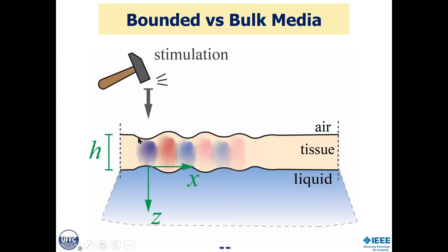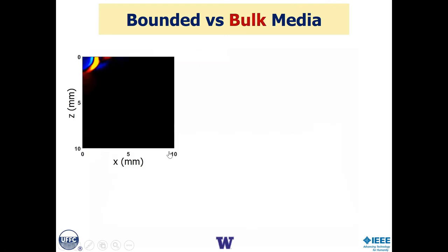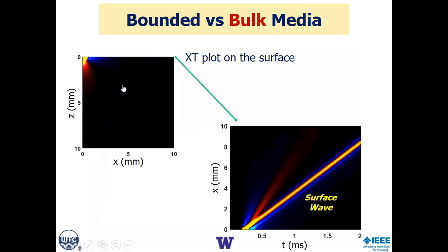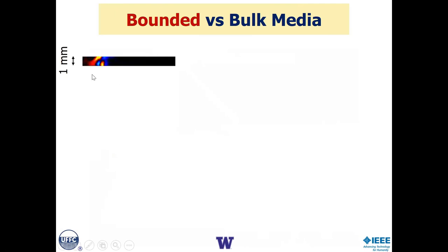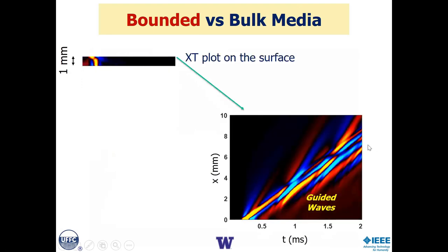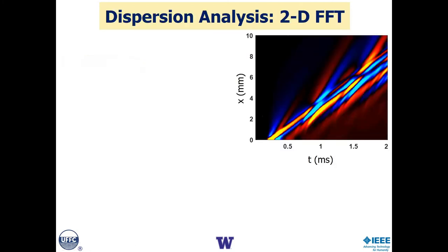It's a bounded material. And its thickness is, even with the broad range of frequencies we use in our mechanical waves, comparable to their wavelengths. So that means we're going to have some level of guiding. If you had this bulk material, we had these two simple waveforms like this and simple wave field plots to look at local wave speeds. However, in a bounded material, we now have reflections from both surfaces that can occur. And so doing so greatly complicates these wave fields. So if you look at local derivatives, it has nothing to do with bulk characteristics, therefore with tissue moduli; the geometry influences that.